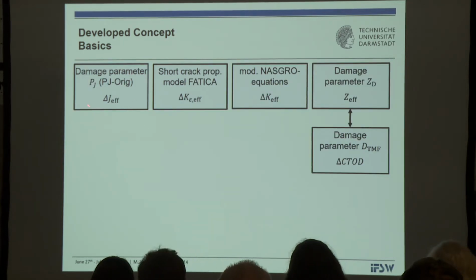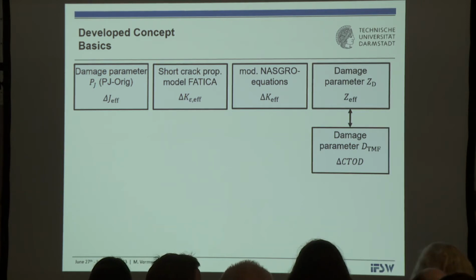So I should mention that not only what I have explained shortly a minute ago, this PJ approach has been performed by others also. I will not have time to go into details here, but I should mention that our research partners in Freiburg very much rely on their damage parameter. And the main difference is that they say the crack driving force is the cyclic version of the crack tip opening displacement, and we say it's a J integral, but there are relations between both, and the differences are not too large.